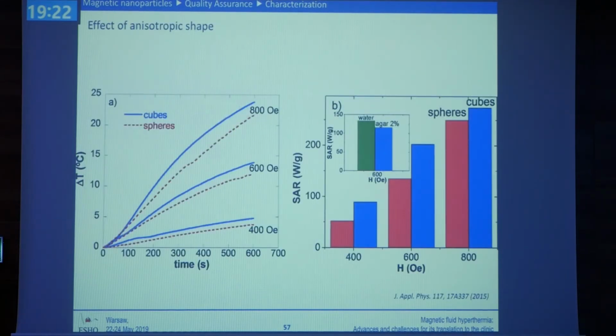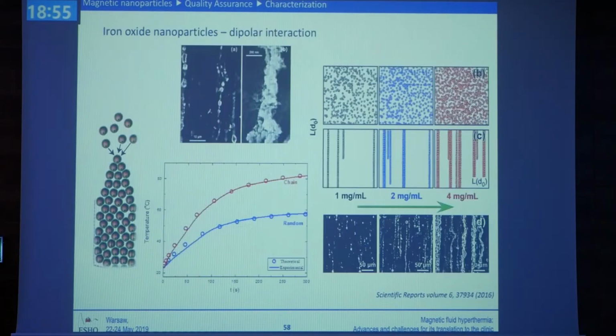Okay? Of course, the shape of the nanoparticles plays a role. This is a result from the Hariharan Srikanth group in University of South Florida, where they have created spheres and cubes, and because the anisotropy of the cube is higher than the anisotropy of a sphere, actually the sphere doesn't have any anisotropy, but the cube is an anisotropic shape, then you have a higher SLP for the same magnetic field.